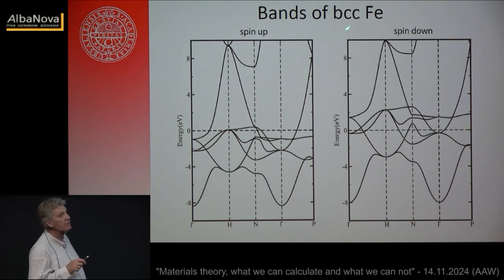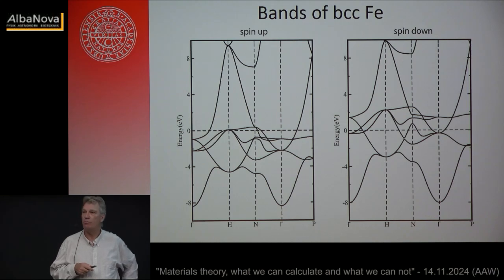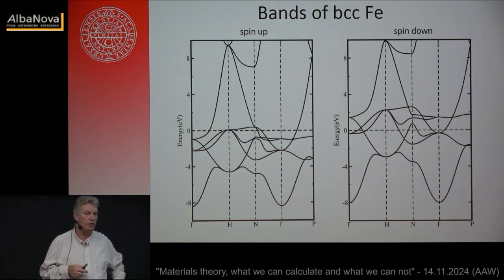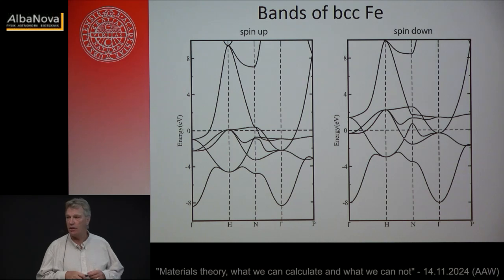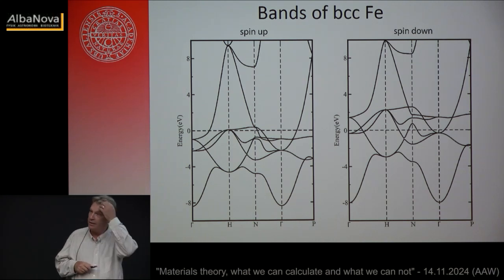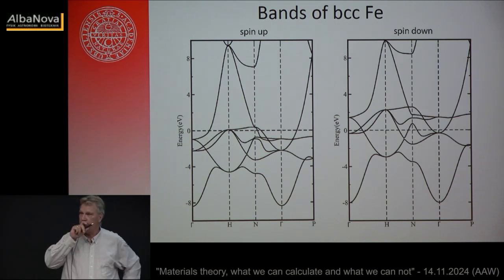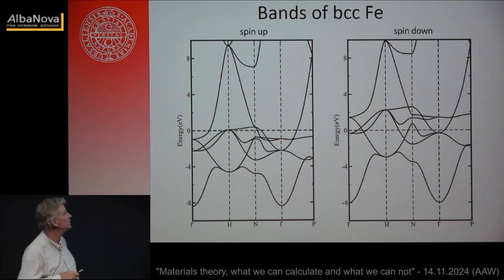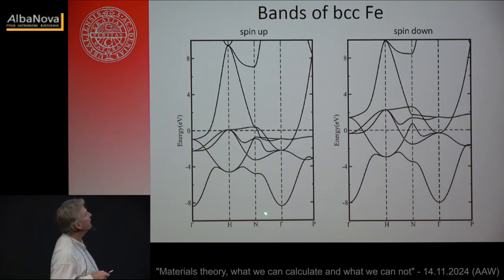And this is now for BCC iron. It's a system that spin polarizes. The functional itself favors an energy where there's an asymmetry between spin up and spin down particles. BCC iron prefers to have a little bit more spin up than spin down. And you can see it here. All electron states here now are filled up to a common Fermi level that's now at zero energy. This is now in electron volts.